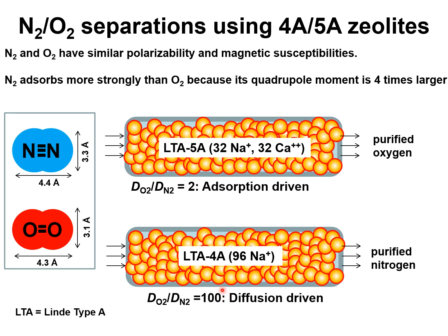The net result is that the differences in the intracrystalline diffusivities serve to override the adsorption selectivity advantage that is in favor of nitrogen, and the pores are richer in oxygen that has the higher diffusivity value, and the separation is diffusion driven.